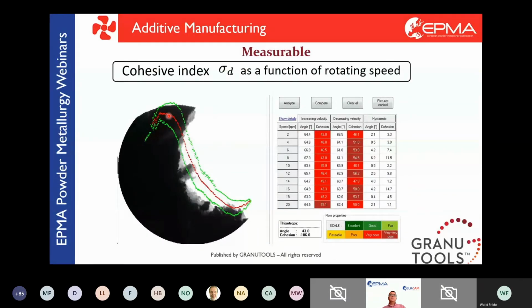What you see in red is the average interface. And what you see in green are the maximum and minimum - technically a specific formula, the least square method, but basically maximum and minimum. The area between the maximum and minimum is one of the parameters used to measure the cohesive index.